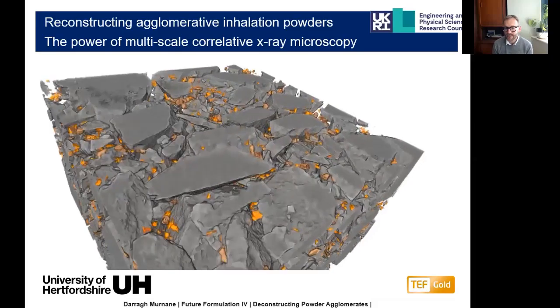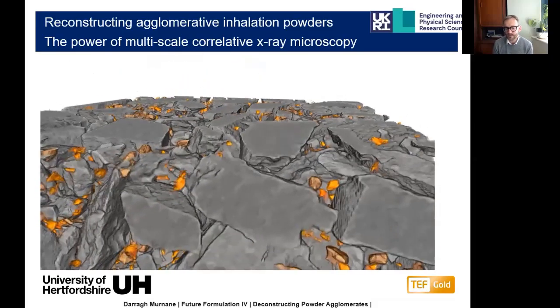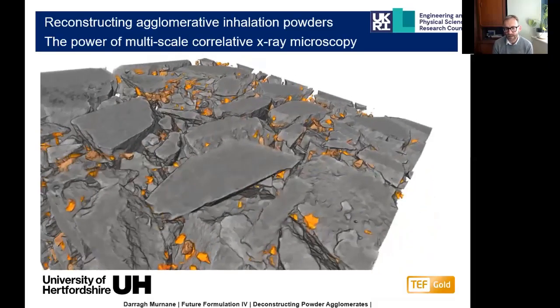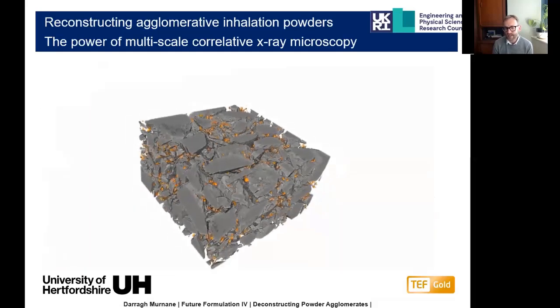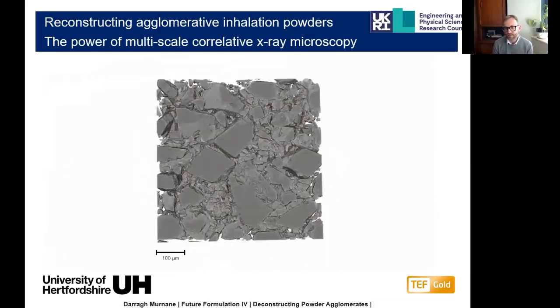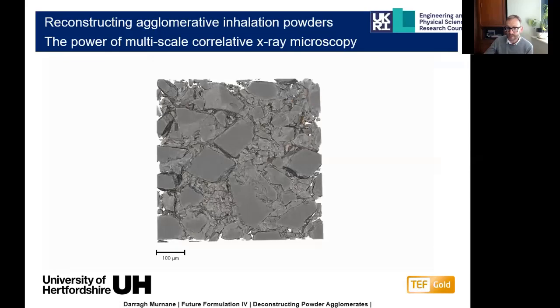So we can see this is the first time where we've really been able to look inside a bulk powder as it would be filled into a blister and identify where those very fine particles are located within that blend. And that's important to us because it builds up an image of the porosity of that blend to airflow. It allows us to start looking at where the high surface energy particles are distributed, and it allows us to start building up a model of how those particles are going to behave during blending and during aerosolization processes.